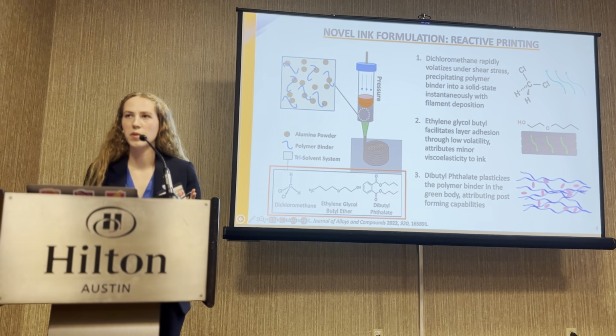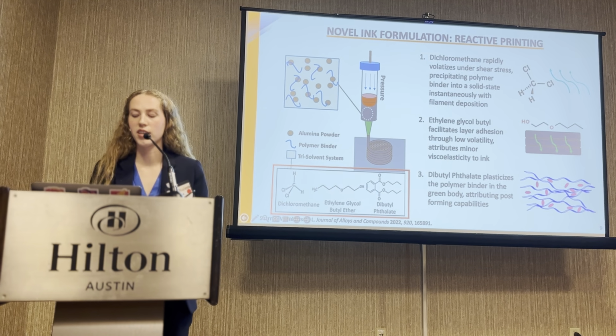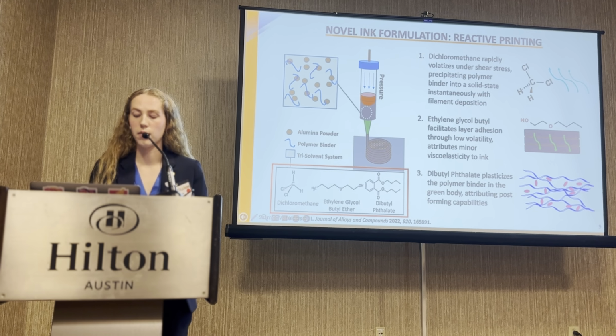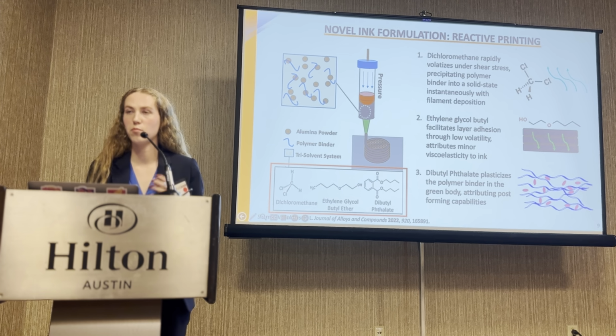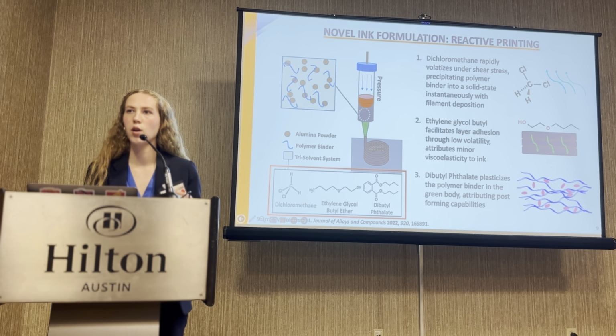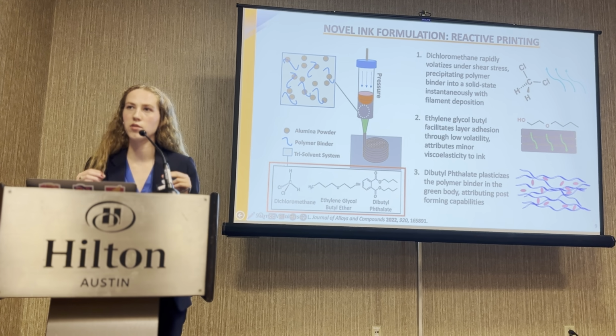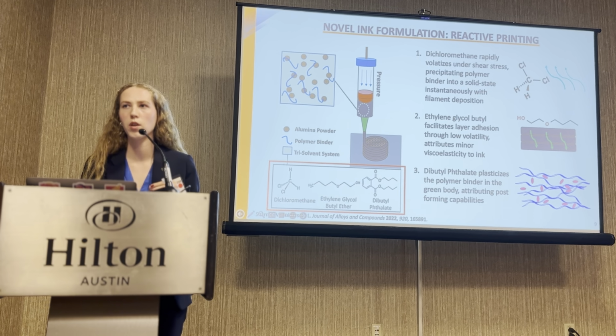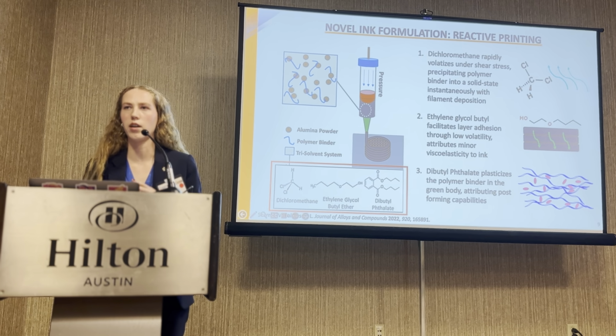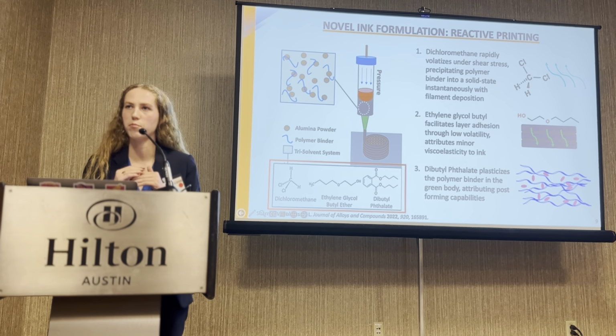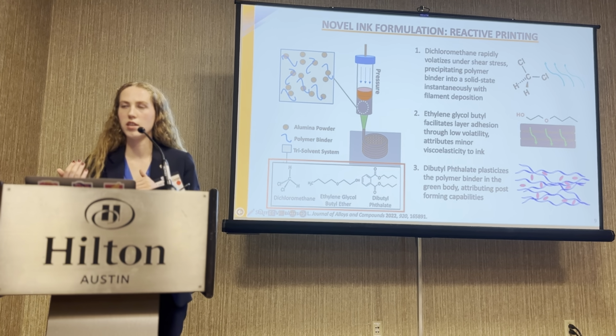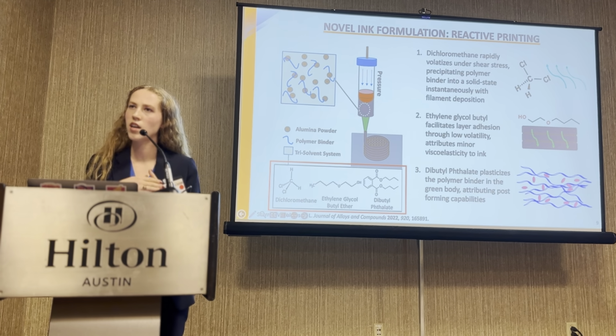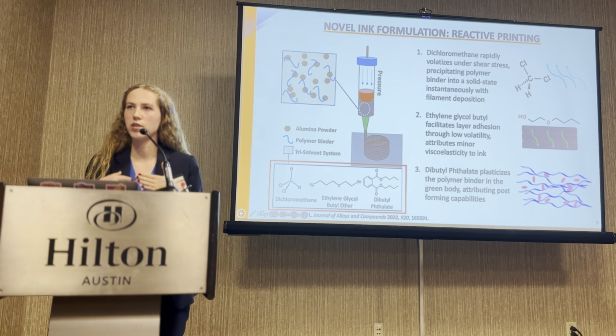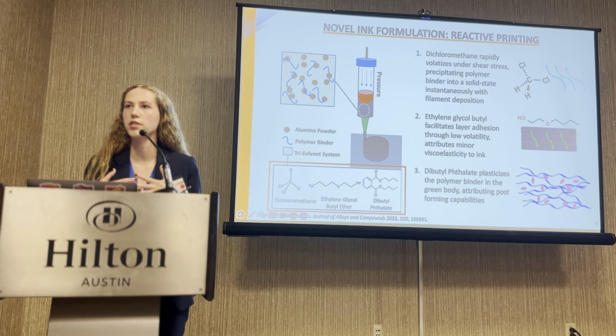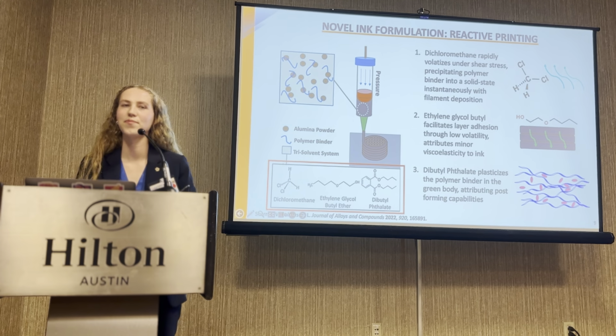So the DBP, the dibutyl phthalate, is a plasticizer, and the EGBE has a low volatility, which means that between those layers, it keeps it from setting too quickly. So you have the dichloromethane, which allows it to set in order to maintain that shape. But the EGBE tempers it a bit and allows the layer boundaries to fuse into each other before fully setting.